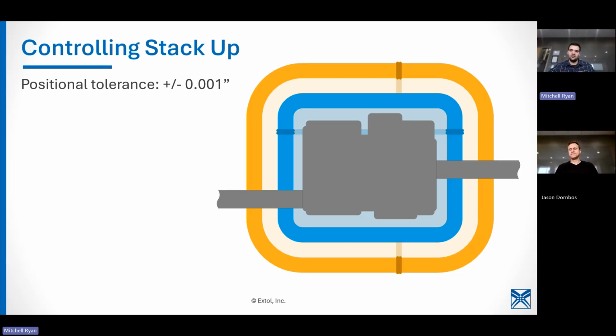So the additional benefit of planing those surfaces flat is we can control the stack-up tolerance. So this is one application we have, or one of several types of applications where you've got a part encapsulated in a housing that may have areas that protrude into another portion of the assembly. So you've got stack-ups internally that you need to control on the weld process. And you've got maybe some other parts that are encapsulating the outside of that part. And then that goes into a larger assembly.